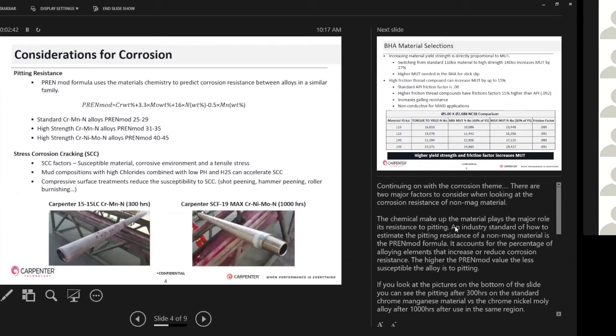So there are two major factors to consider when looking at corrosion resistance of a non-mag material. The chemical makeup of the material plays a major role. The industry standard that we use is the PREN mod formula for pitting resistance. It accounts for the percentage of alloying elements that increase or reduce the resistance to pitting. The higher the PREN mod value, the less susceptible that alloy is to pitting.